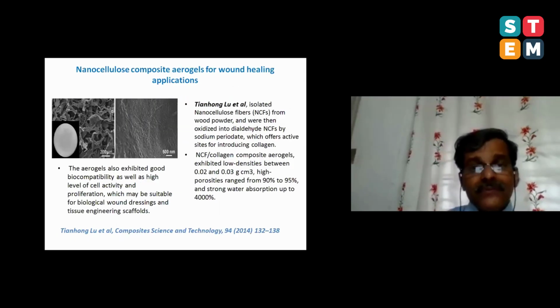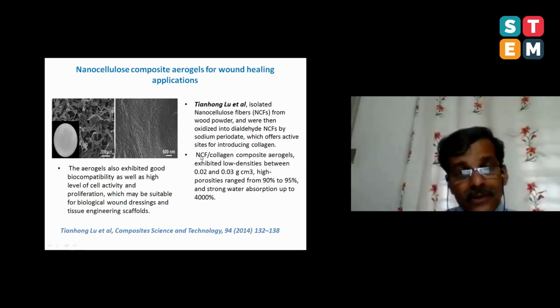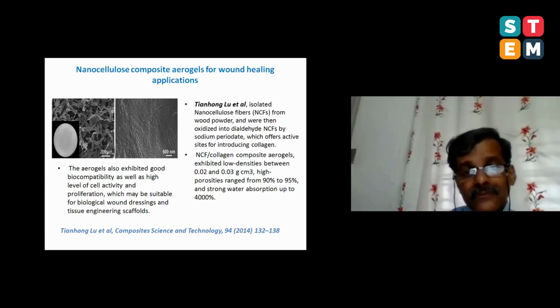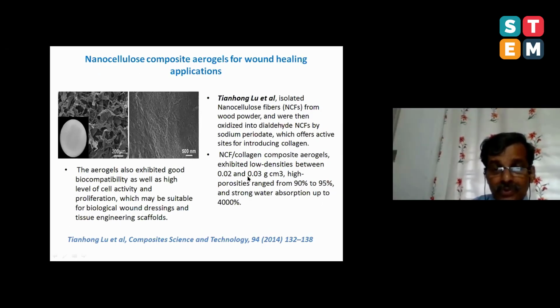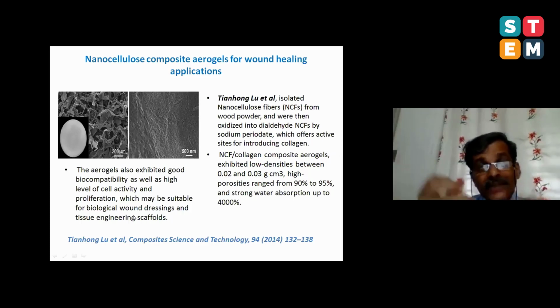Let me show you another slide of Professor Lu and group. You know what they made? They made a composite of nanocellulose and collagen. When you make a composite of nanocellulose and collagen using the aerogel technology, they made a beautiful aerogel. Look at the density of the aerogel, 0.02 to 0.03 gram per cubic centimeter, and extremely porous. And water absorption capacity is 4,000%. And this is an excellent platform for wound healing applications. So nanocellulose, collagen. Why is collagen added? Because when you have collagen, the tissue compatibility is excellent. So they were very, very successful using this material for cell proliferation, angiogenesis, and cell growth.